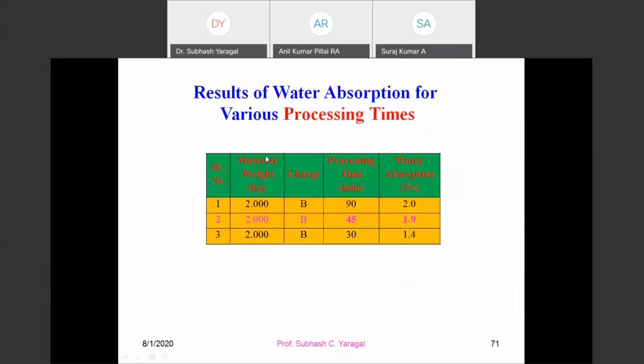And the third and last part is results of water absorption for processing times. For processing time, we have studied half an hour, 45 minutes and 90 minutes. You have the least water absorption for 30 minutes. So this study we have highlighted.